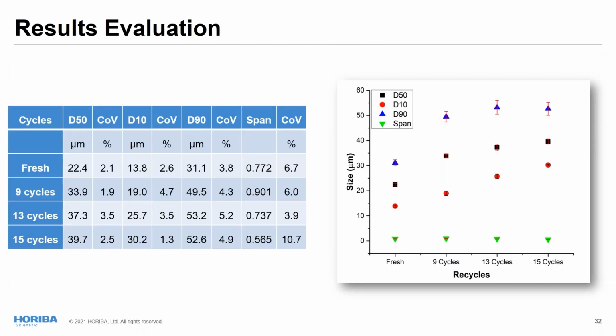So here I'm plotting all the data, and Matthieu was talking about heterogeneity of the sample, especially when you increase the recycles. When you have an established methodology, you can trust your coefficients of variance, as you can see here. For the fresh sample, the repeatability is really good, so the coefficient of variance is low, 2%. And you see it starts to increase a little bit, especially at larger sizes for the recycles, which means the homogeneity of your sample is not that good anymore. Again, this comes back to ISO having a specific way for you to sample your material to increase the representativeness of the sample you're analyzing.